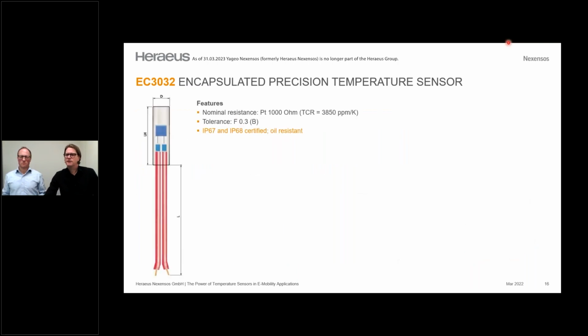If we speak about the precision in that situation, we have also included a PT 1000 with the typical TCR. We have a tolerance class of B available. We have protection against humidity and things like that with IP67 standards tested, and also IP68. And oil resistance is also an important thing I want to talk about later and show you what we made on that topic. The temperature range is not limited by the sensor itself. It's more or less limited by the materials of the cables, of the tip protection, and so on. But we are able to work up to 200 degrees, short term also 250 degrees.